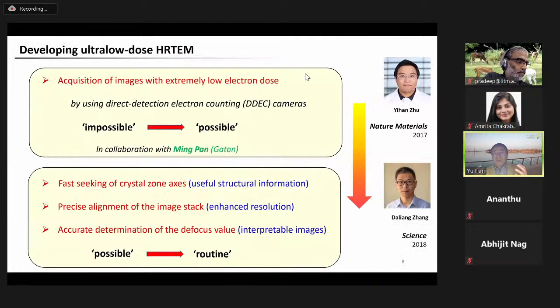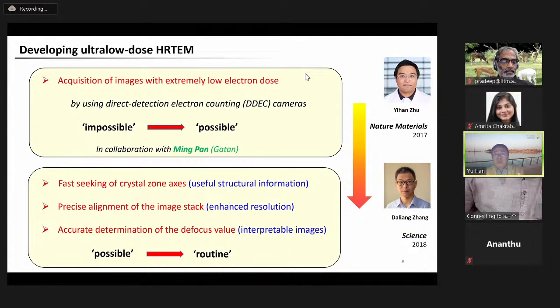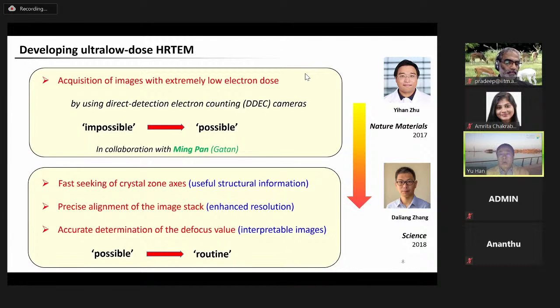So conventional TEM cannot be conducted at such a low dose condition, because with such a low dose, the signal to noise ratio of the image will be too poor to show useful information. This situation is just like taking a photo in a dark room, where, because the light illumination is limited, we can't see much in the picture, right? So to solve this problem, we need to develop a new imaging method, which we call ultra-low dose HRTEM.